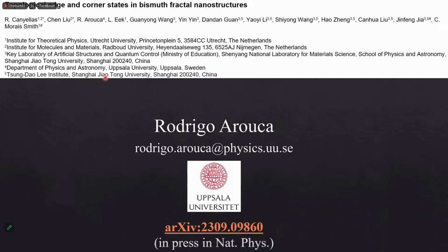So this work started when I was doing my exchange in the Netherlands, in the group of Professor Cristiane de Moraes Smith, during my PhD. As you can see here, there are a lot of people in the paper. It is an experimental and theoretical collaboration. Basically, the group of Professor Jinfeng Jia from Shanghai had some bismuth samples on top of indium antimonide, and they showed that the bismuth flakes on this structure form self-assembled fractal structures.